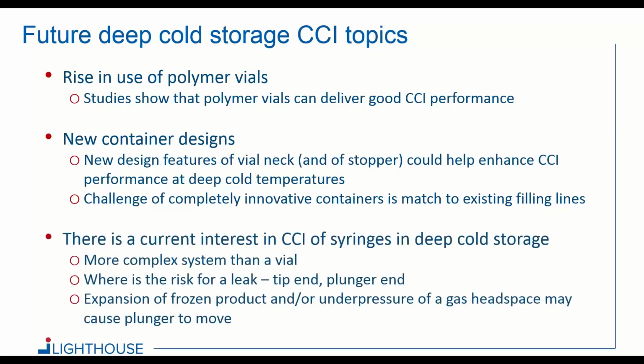And finally, there's also current interest in CCI of syringes in deep cold storage. Obviously, once you fill things in vials, you want to look at how you want to do that in syringes. But this is a more complex system than a vial. You know, where's the risk for a leak? You've got both the tip end and the plunger end. You have all kinds of configurations. If you look at actual product syringes, if you look at the expansion of frozen product and going down in temperature, you get an underpressure of a gas headspace potentially, and these two things may cause the plunger to move during deep cold storage. So more things to do here, and so certainly a lot of work needs to be done in this area in the upcoming period.